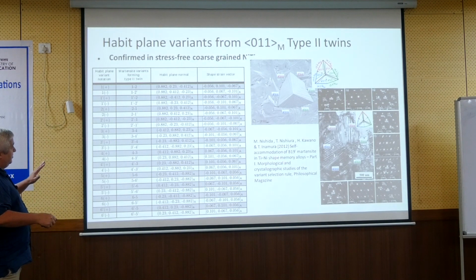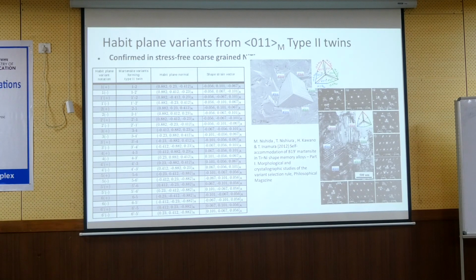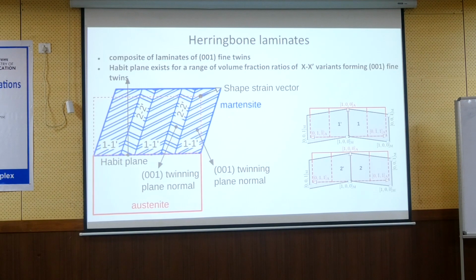This is observed in single crystals, and in polycrystals with large grain size, but it is a little bit complicated, and we have been investigating in the last 5 years the wires with very small grain size, which are most of the wires which we use if we don't put them into 900 Celsius. Those which we buy have very small grains, and here there are also laminates, but a different kind of laminates. The laminates which can be observed in these materials are formed by families of 001 twins. These two twins are on the 001 plane. So these twins are here, and this is the 001 twin laminate. This is another 001 twin laminate, and together they create the habit plane.